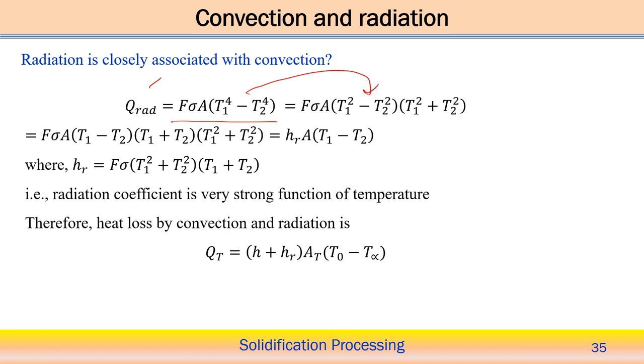Now, we can further expand this one. T1 to the power 4 minus T2 to the power 4 equals T1 square minus T2 square into T1 square plus T2 square. Now, T1 square minus T2 square we can further expand: T1 minus T2 into T1 plus T2, into T1 square plus T2 square. Now, we can introduce it in such a way that this temperature factor, together with the other factor F into sigma, can be considered as h_R, so that Q is h_R times the cross section area into T1 minus T2. So, h_R is effectively F sigma into T1 square plus T2 square into T1 plus T2. So, mathematically if we express it like that, h_R is the radiative heat transfer coefficient, and then we can add in the convective mode of heat transfer by estimating the different values of the heat transfer coefficient in these cases.